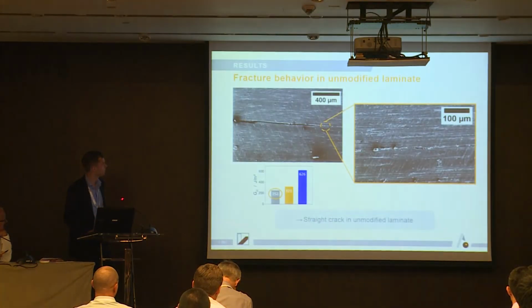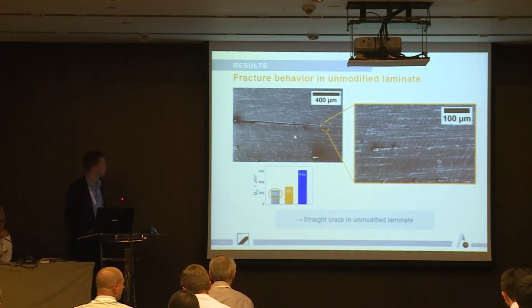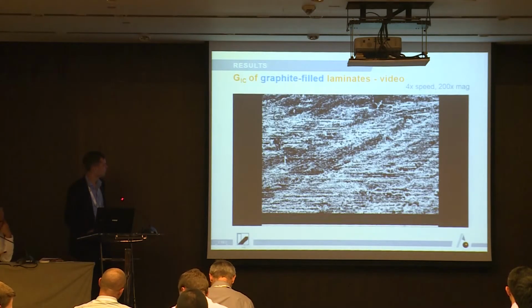So this is just a very basic observation of the neat material. When you look from lower magnification, you can also see that the crack is really straight moving through the material. Also at higher magnifications, you still see the crack is quite straight. Then when you have the modified material, with slightly higher fracture toughness, you can also see the crack moving from the left side to the right side.